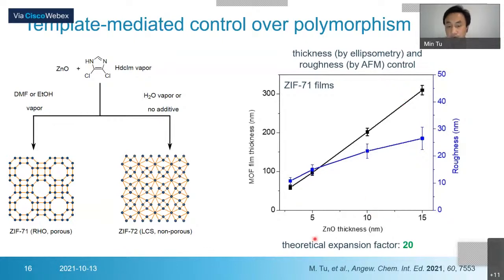So we calculate the theoretical expansion factor is around 20. So if, for instance, we have 5 nanometer zinc oxide, we expect to get 100 nanometer ZIF71. The black one corresponds to the film thickness. So we can see we can have a good control of the MOF film thickness, and the roughness is not too high, but with the increase of the MOF film thickness, we can see the roughness is also going higher. So then we come to the question, what's the reason behind this?